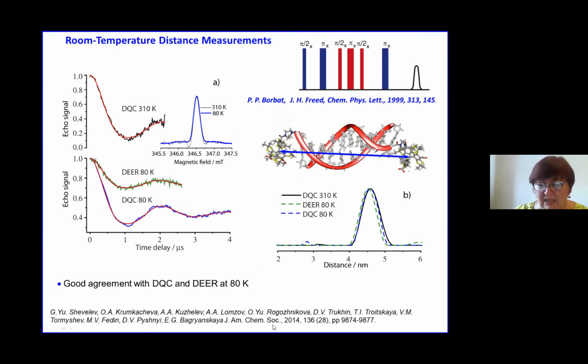So, that was results quite some years ago. In 2014, we performed the first work where at room temperature we measured distance between a nitroxide spin label and trityl. This work really attracted a lot of interest, many citations. The main result of this work is validation of the PELDOR measurement in frozen solution, because here you see distances at low temperature and high temperatures were the same.